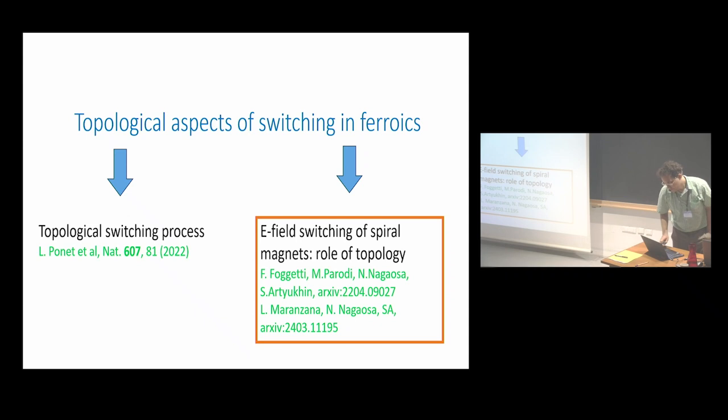Okay, then this is the mechanism that was discovered experimentally that's working at very low temperatures, right? At only 2 Kelvin, this material works because the rare earth in gadolinium manganite orders at very low temperature. But it gives us the hint that maybe one could make more interesting and also potentially efficient memory devices based on this switching.